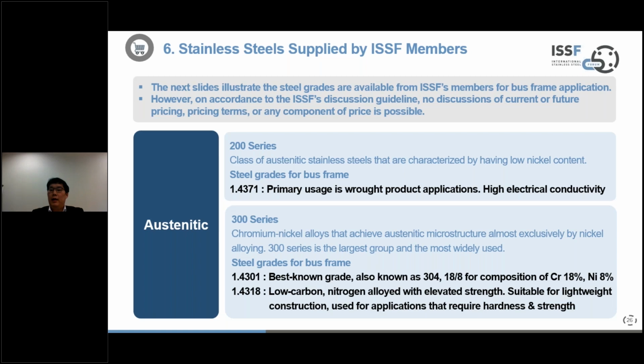It's a chromium nickel alloy that achieves austenitic microstructure almost exclusively by nickel alloying. And by the way, 300 series is the largest group, it's the most common one when it comes to stainless steel. What do we have? Well, we have 1.4301, otherwise known as 304, 18/8. It's the best known grade, it's the bread and butter of stainless steel, it's the most common grade. It has a chromium percentage of 18%, nickel 8%.